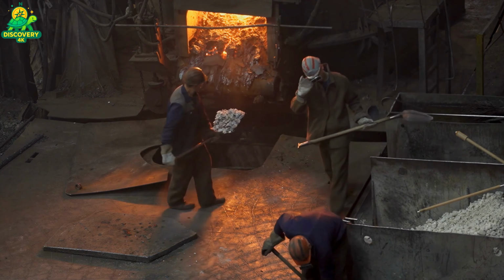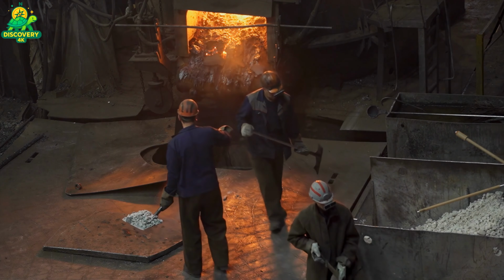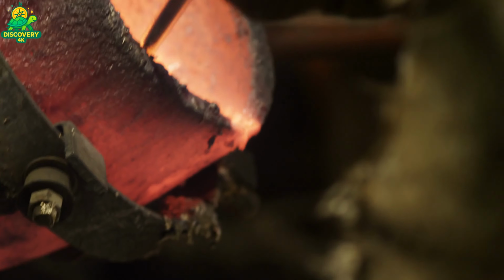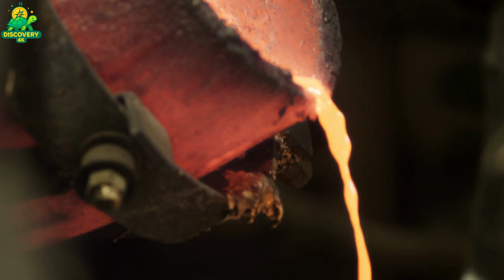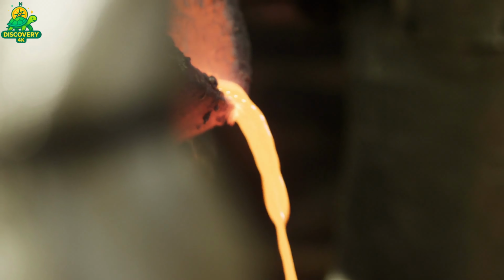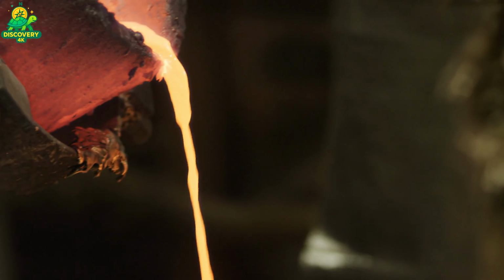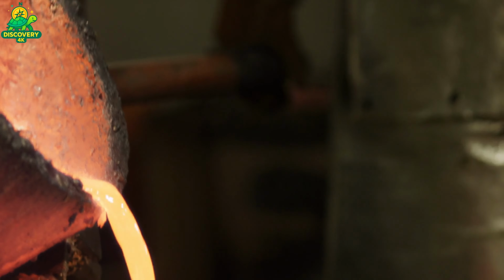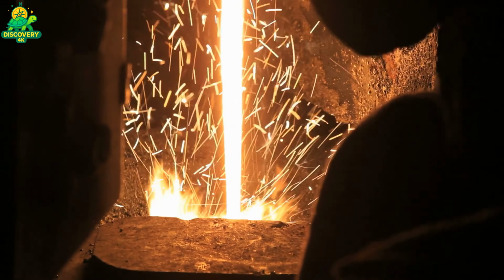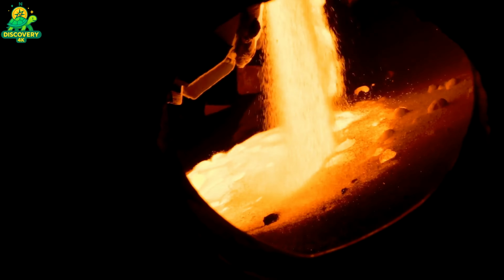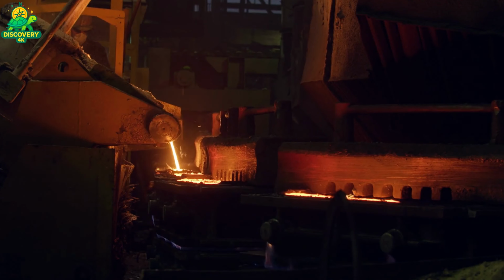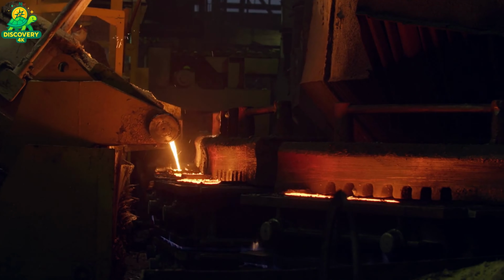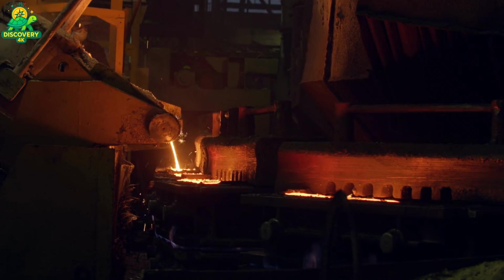To achieve the ideal balance of strength and ductility, alloying elements are added: carbon to control hardness, silicon to improve castability, manganese to increase wear resistance. Each addition is carefully calculated, as even slight variations can affect the performance of the finished manhole cover. Within hours, the once jagged scrap transforms into a shimmering molten mass. When the composition reaches perfection, workers prepare for the next step: pouring.